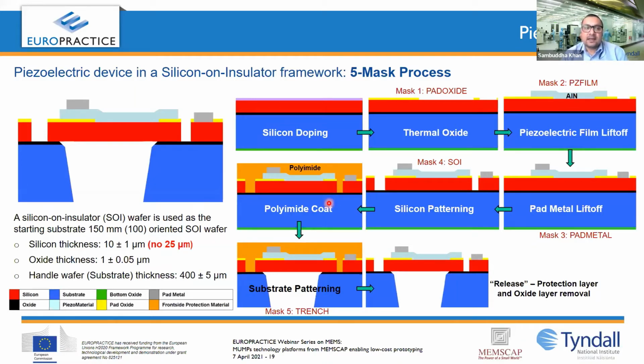It's a 5 mask process, and this is also a silicon-on-insulator based process, where, in addition to the silicon-on-insulator processing, a piezoelectric layer is deposited on top of the silicon layer, and thereby you end up getting piezoelectric devices. So it starts with a silicon-on-insulator wafer, but the difference between PiezoMUMPs and SOI MUMPs is that the silicon thickness is available here only as 10 micron, the 25 micron option is not available here, and the oxide is 1 micron as it was for SOI MUMPs. Handle wafer thickness is 400 micron. The process is almost the same, but some differences are there, so I'll talk about it.